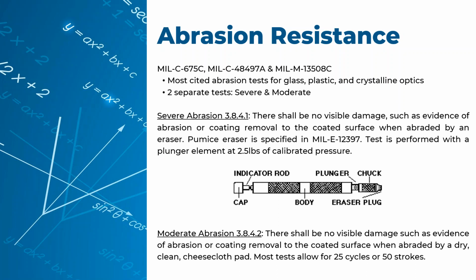Almost all coatings are going to fall into the moderate abrasion mode, and that is essentially 25 cycles or 50 strokes of a cheesecloth, just a clean, dry cheesecloth that you'll run across the coated surface. You measure basically, how does it look before I do it? How does it look after? You can measure it with a spectrophotometer if you want to see if there's any loss in transmission, but more than anything, it's a visual check.